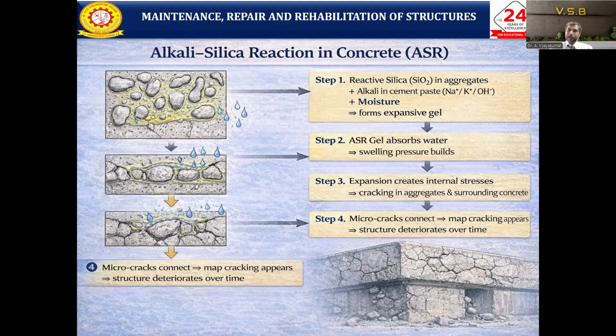If we have any micro cracking or cracking, moisture starts to penetrate and immediately the chemical reactions start. Because of this chemical reaction, there is expansive gel formation surrounding the aggregate. With continuous water absorption, the gel thickness surrounding the aggregate keeps increasing like a bulb. So swelling with pressure, it's a bulb. What will happen? Tensile cracks will occur. Internally, the expansion creates internal stresses. So there is cracking in the aggregate and the surrounding concrete, and tensile cracks occur around it.